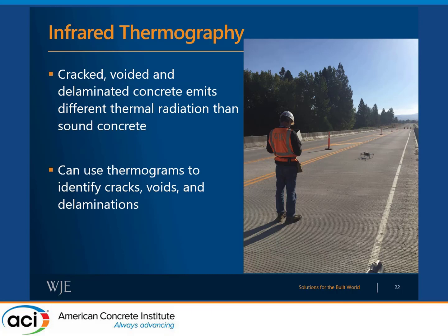The other application I mentioned before is infrared thermography. So basically the reasoning behind this is that cracked, voided, and delaminated concrete have different thermal radiation that they emit relative to sound concrete. And I'll show that in another slide. We can use that to identify where cracks, voids, and delaminations are.